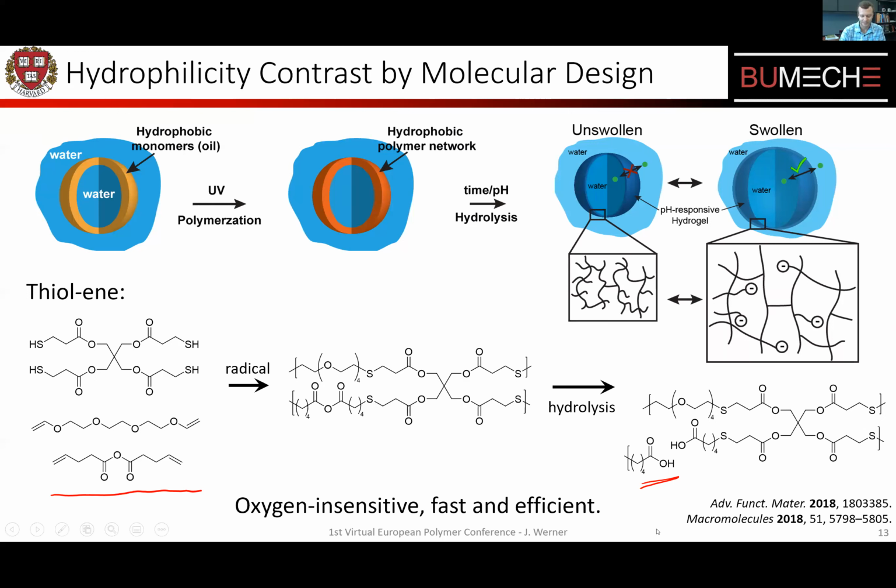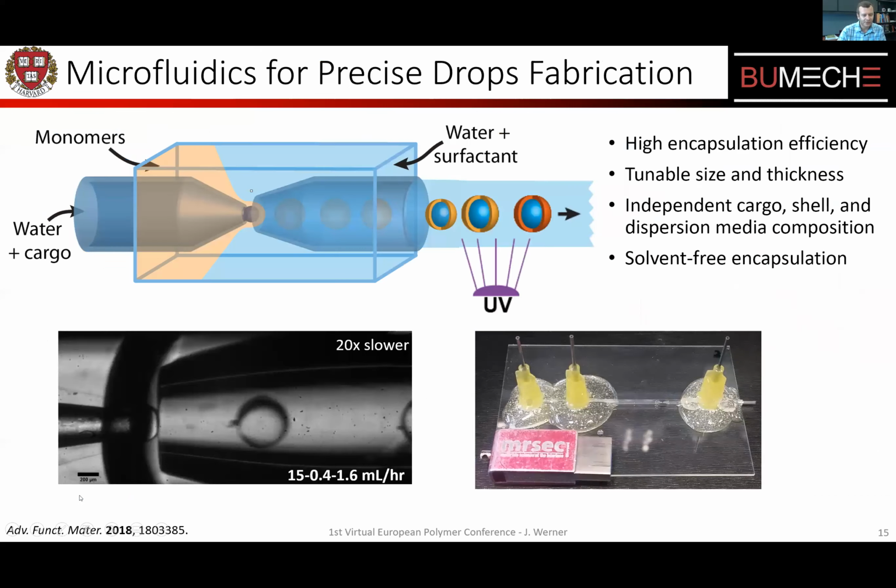Macromolecules paper down here. Now, a little more about these devices, because a lot of you might not have seen these before. One way to make microfluidic drop makers is simply using glass capillaries. And on the bottom right here, I show a picture of them, and that is truly how simple they are. You use glass capillaries that are tapered on one side, and you can control the size of this taper, which has an influence on your particle size.